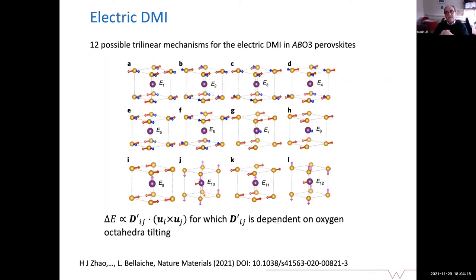We didn't analyze that from the DFT point of view because it's very difficult to do DFT on such a big scale system. We don't have the infrastructure for that, nor the knowledge. So we're very basic. But we think one of those, especially this E7, will be able to give us this. So you see that we have opposite, then in plane, then out of plane, and then in plane, which will kick the polarization to swirl.